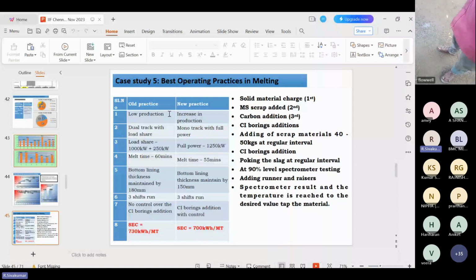So earlier the melt timing was 60 minutes. Now it is 55 minutes only. 5 minutes is saved, and always the bottom thickness is maintained at 180 mm. Here they maintain 150 mm. 3 shifts are running. So the specific energy consumption is reduced from 730 to 700 units.